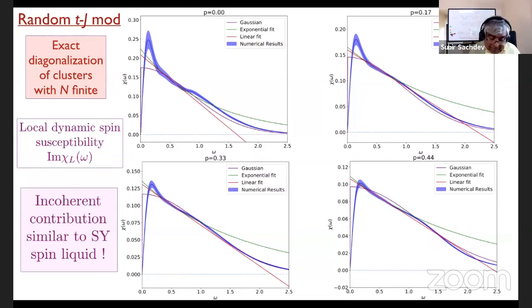Okay, and of course, this incoherent contribution here, the finite omega, seems to persist all the way up to the critical point. In fact, it even looks better here. So that's really very nice. There's some indirect evidence, fairly direct evidence, I would say, of SYK physics with the time reparameterization mode and the discontinuity at zero frequency showing up in the numerics at this critical point. And that's a very robust prediction of the SYK physics, the linear in omega dependence and the discontinuity at zero frequency. As a reminder, in a Fermi liquid, this would just go to zero.